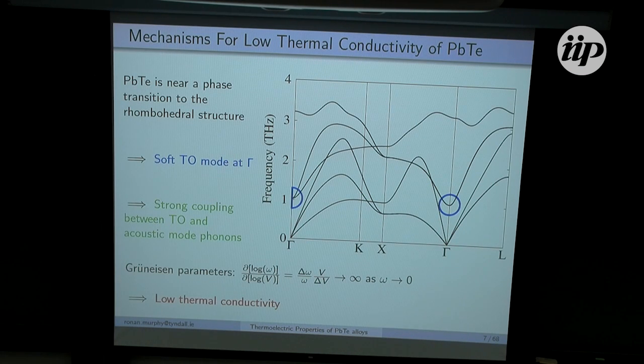So to demonstrate this, I have the phonon band structure here of lead telluride, and because it's near this phase transition to the rhombohedral structure, it has a very soft TO mode at the gamma point. I've highlighted it here. It's about 1 terahertz. Now, because this mode is so soft, it couples very strongly with acoustic mode phonons.